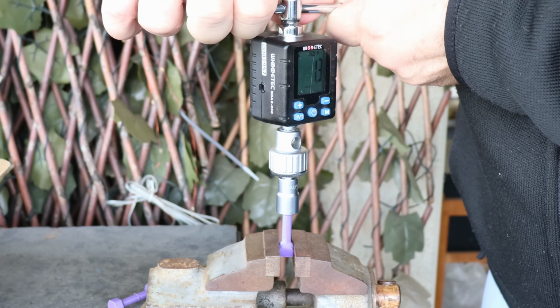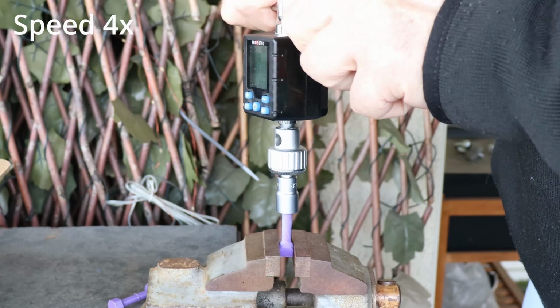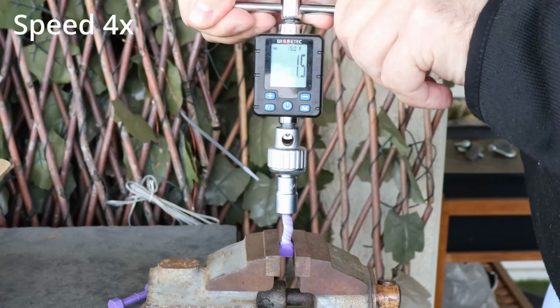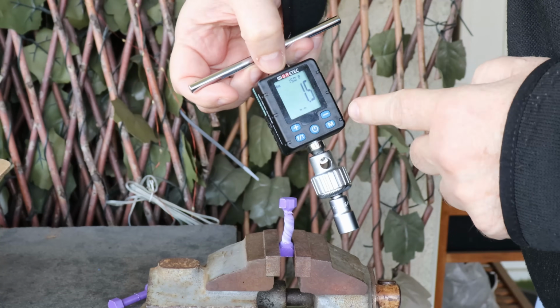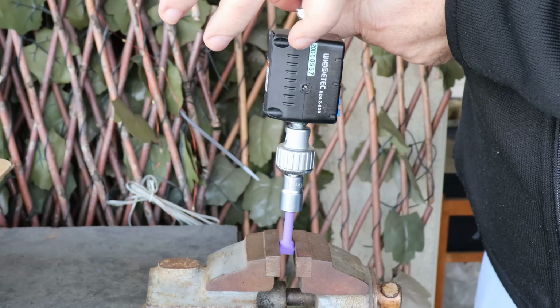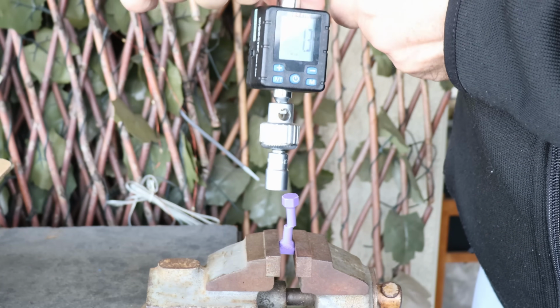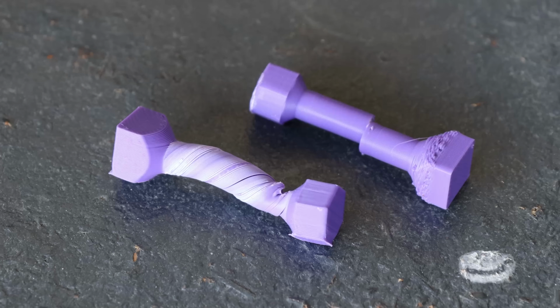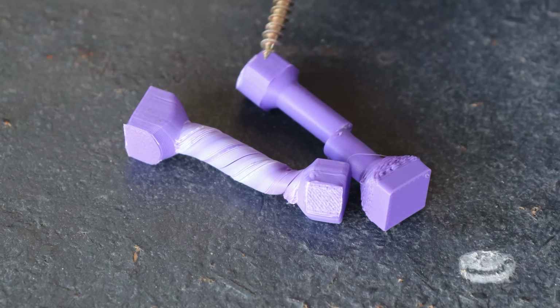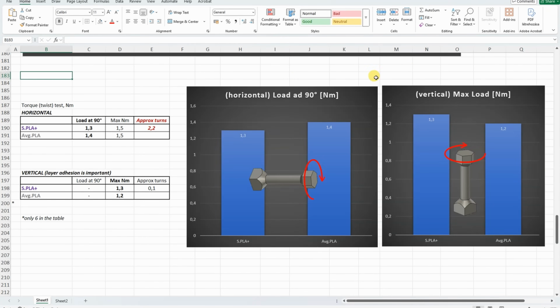Torsion test, I'm starting with horizontal printed object. 1.3. Load and 90-degree rotation. And the maximum load. 1.5, the peak. Printed in vertical position. 1.3. The numbers are similar, but huge difference in break types. In both cases the difference is not big, but exactly in direction which is expected. So printed in horizontal position, the load at 90-degree rotation, average PLA was stronger compared to the Super PLA Plus, but in vertical position where the layer adhesion is important, the Super PLA Plus was better compared to the average PLA.